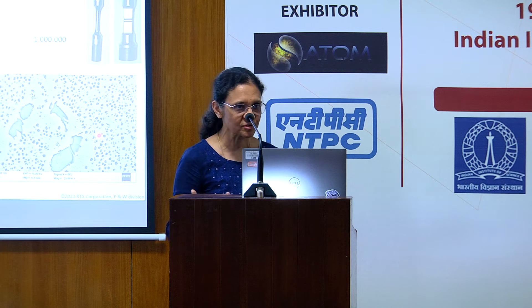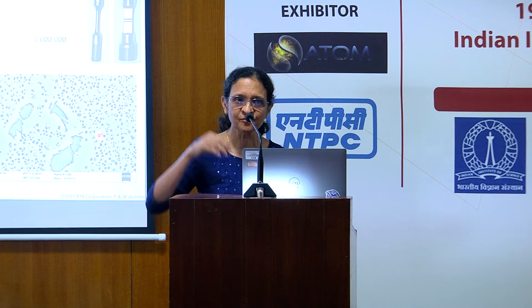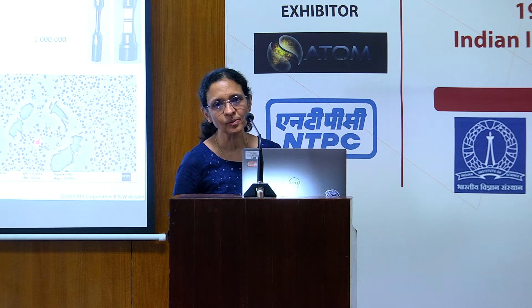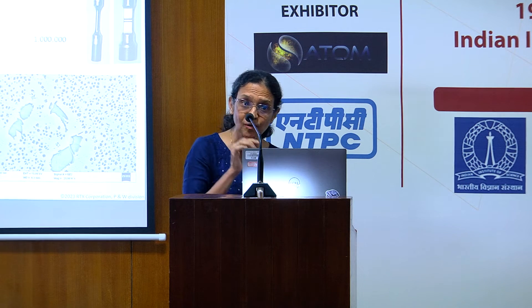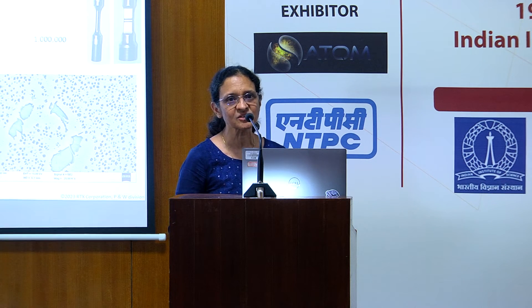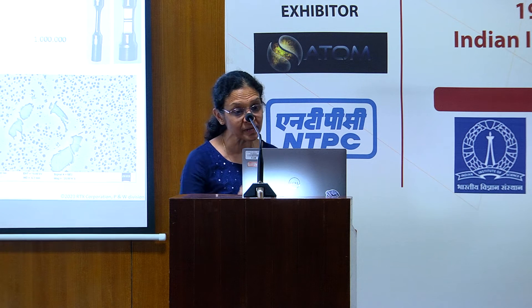This is a nickel-based superalloy microstructure that has gamma and gamma prime — the strengthening phase. First, what happens is you get a precipitate-free zone right at the top wherever there is pit formation. Pitting is not going to be uniform. It forms an easy path not just for intergranular cracking, but more importantly, oxidation in the grain boundaries, which is worse. Even a crack can be arrested by the strengthening precipitates, but the oxidation that takes place leads to more sulfidation. It's mind-boggling to see the reaction kinetics at that reaction zone.